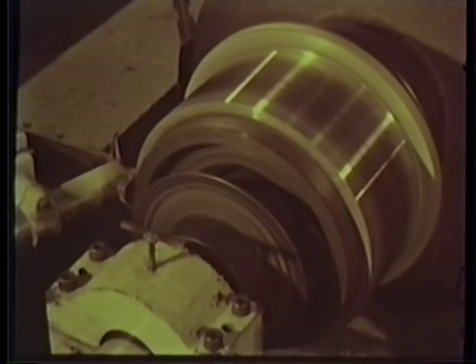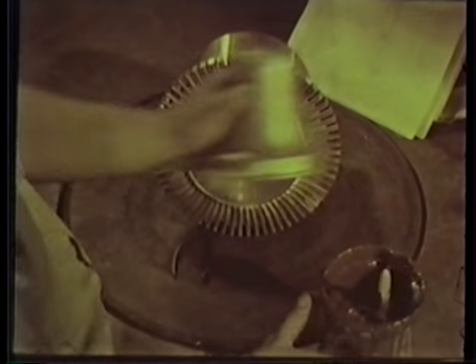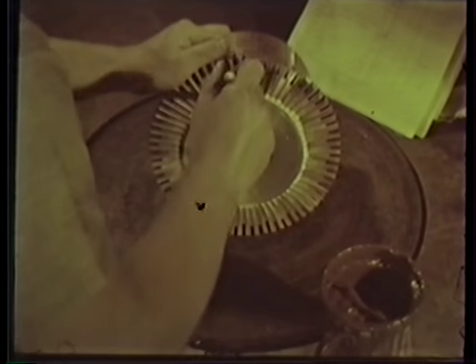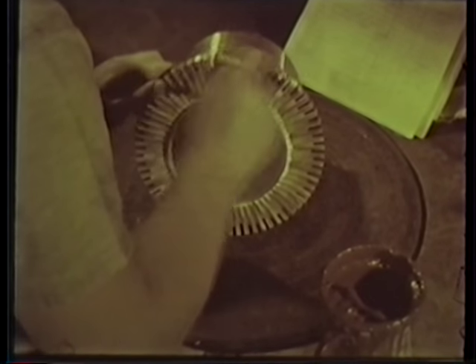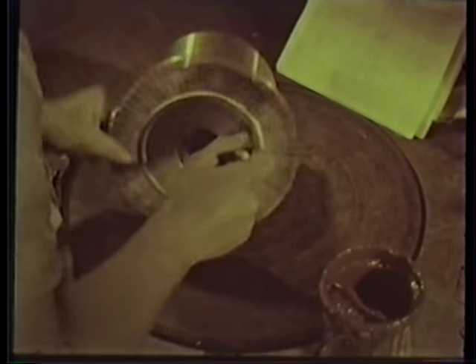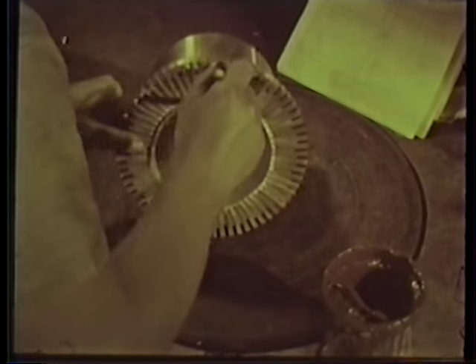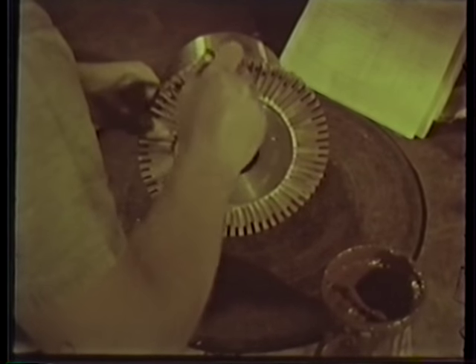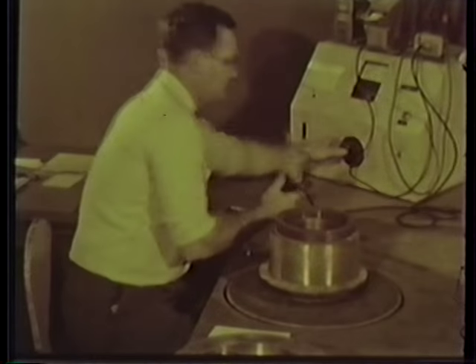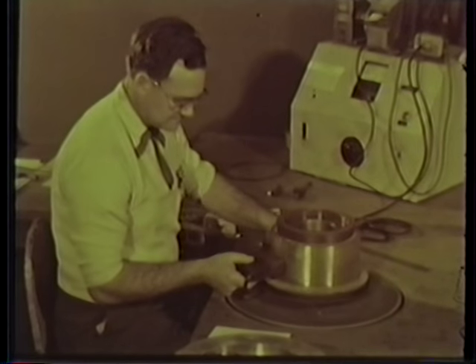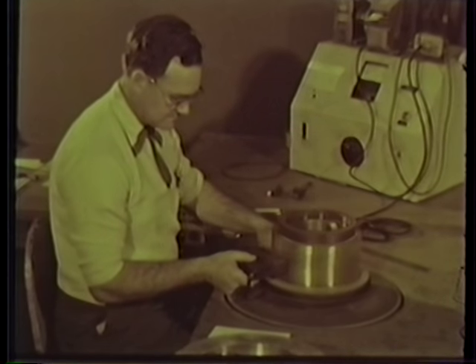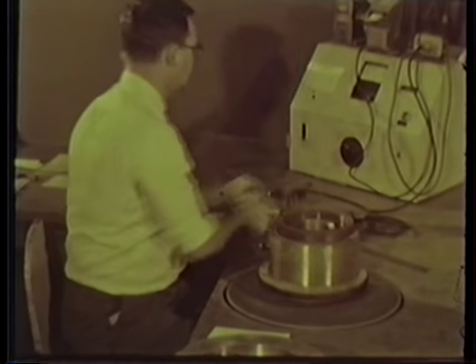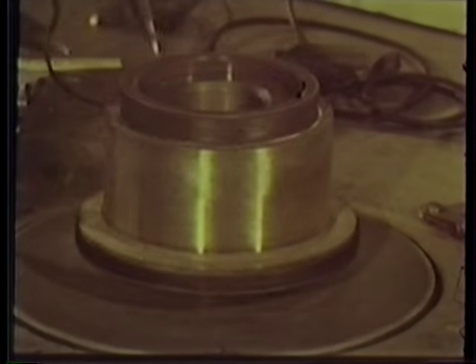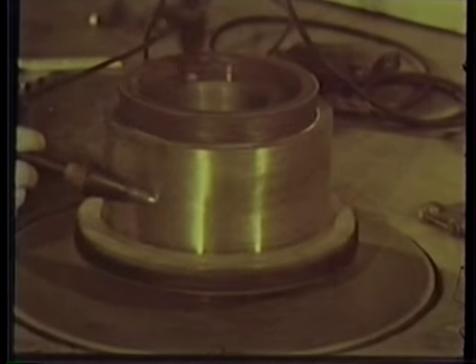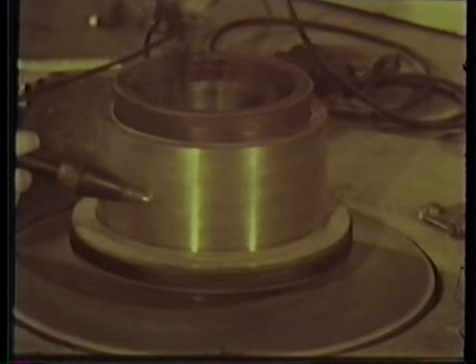A final surface finishing step takes place while the commutator is still mounted on the spin table. With spin seasoning completed, the final step is the application of an insulating and heat-resisting varnish to all non-working parts. This gives added protection during long periods of shelf storage and use. At the final inspection station, all mechanical dimensions are checked against the prints once again, and the commutator subjected to proper bar-to-bar and bar-to-ground short test with both AC and DC test equipment.